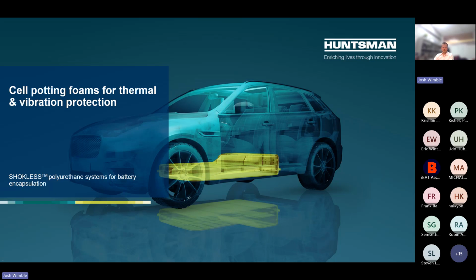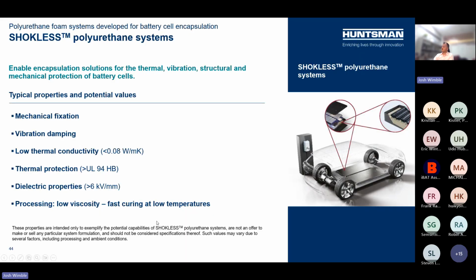Okay, so now I'm getting to the potting foams, which is what people most often come to us about because of our success in this field. So cell potting foams, or sometimes they're called cell encapsulation resins, serve a really different function depending on who you're talking to. Most use them for some level of mechanical fixation or vibration damping of cells, especially with cylindrical cells. They're great at being a very processable, very manufacturing friendly solution for pouring in and quickly curing and keeping your cells protected. Some OEMs use them to improve the pack or module stiffness, so use higher stiffness foams that can contribute to the mechanical properties of the overall pack, while many focus very specifically on the resin's role in mitigating thermal runaway propagation.